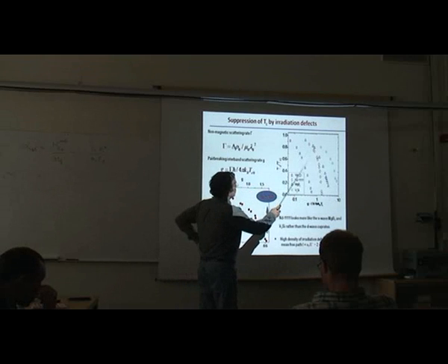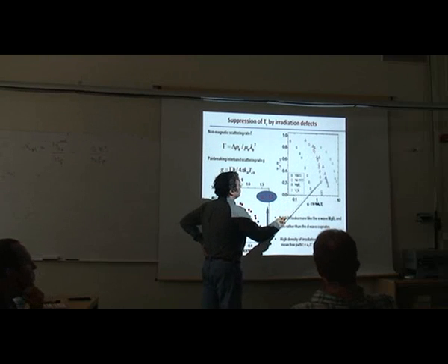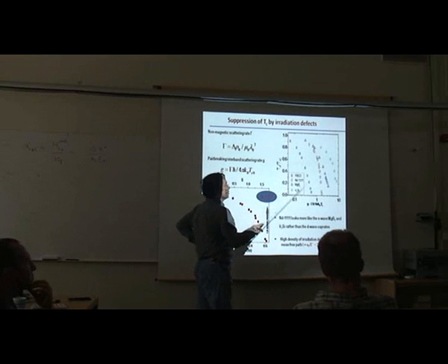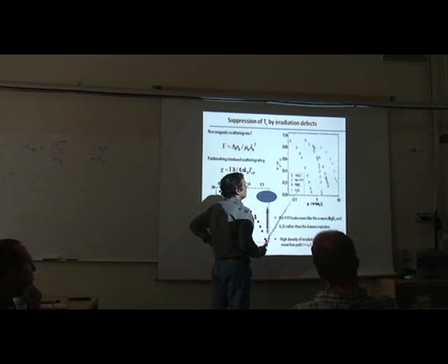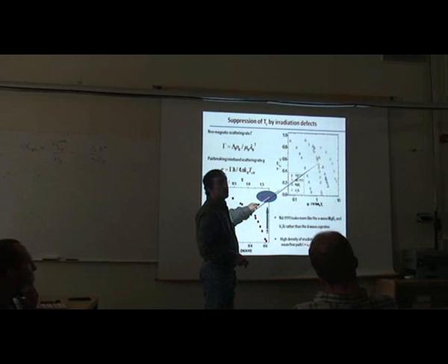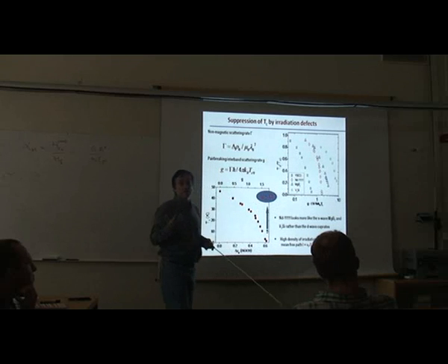So here, red is our sample. This blue triangle shows MgB2. YBCO is this, the blue squares, and this is more conventional V3Si. What it shows is that our pnictide crystal behaves more like a conventional MgB2 crystal than the cuprate. And the cuprate is a lot more sensitive to the irradiation disorder than this pnictide.